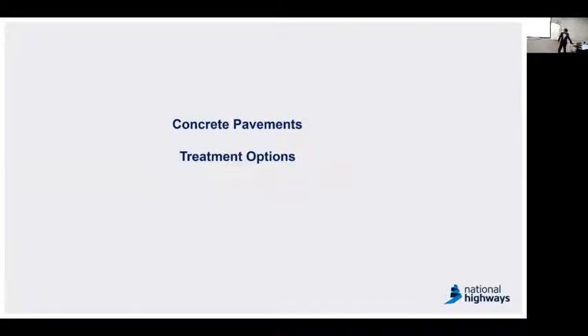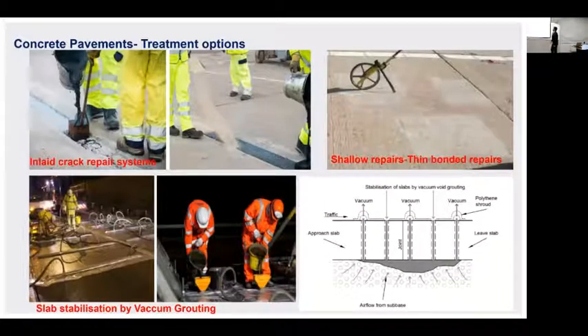Now I would like to talk a little bit about the common treatment options. For treatment options, the first one on the left-hand corner is inlay crack repair systems. For example, if you have a crack, you could think about inlay crack repair systems, where you are basically getting an emulsion, and that's one of the systems that you can easily use. The second one is basically using calcined bauxite on top of the emulsion that we put on. It's mainly to improve the skid resistance for that particular patching. And the one on the right-hand side is shallow repairs. For example, if you have a very superficial defect, but you still need to get it done, you'll be looking at around 20 to 40 mm deep. So that's your shallow thin patch repairs.